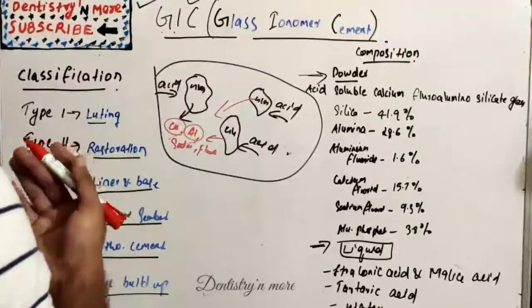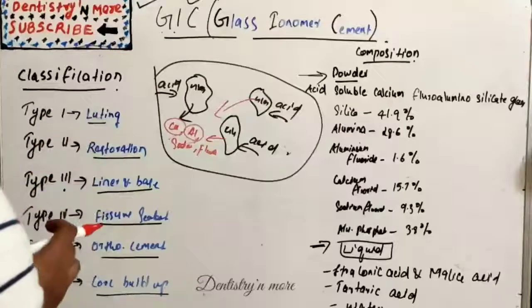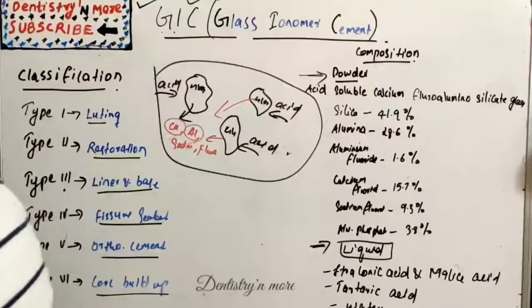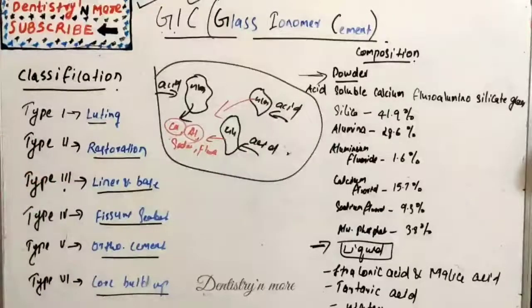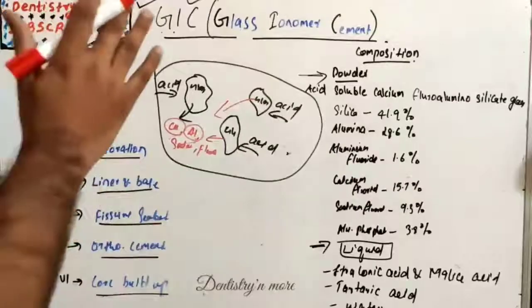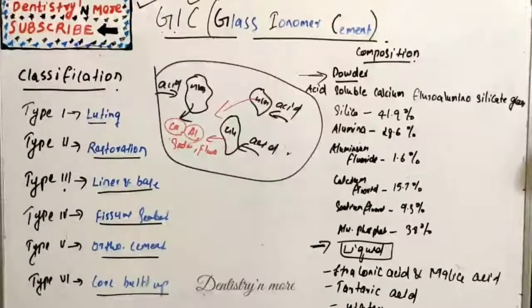Water plays a very important role in the structure of cement. After hardening, fresh cement is extremely prone to cracking and crazing due to the drying of loosely bound water, hence the cement must be protected by application of varnish or vaseline. We used to apply vaseline over the newly created restoration.